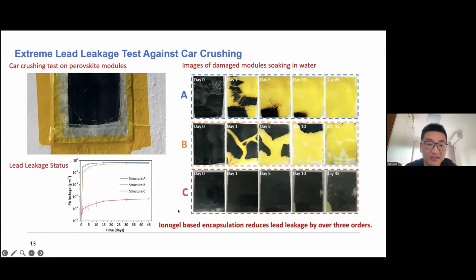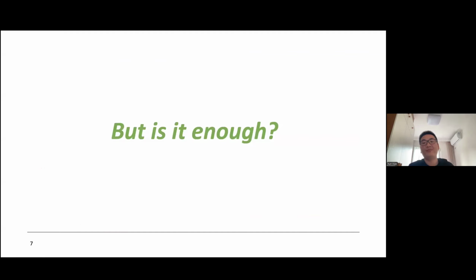But for the lead leakage test, we could see it's still around 3 orders of magnitude lower than the commercial one. So we think it's a very good encapsulant against lead leakage for our ionogel. So it's very exciting for us to handle this lead leakage. But when I went to Linköping to do more research on perovskite solar cells, I was thinking about what I can do more, or is it enough for perovskite solar modules to enter the market?